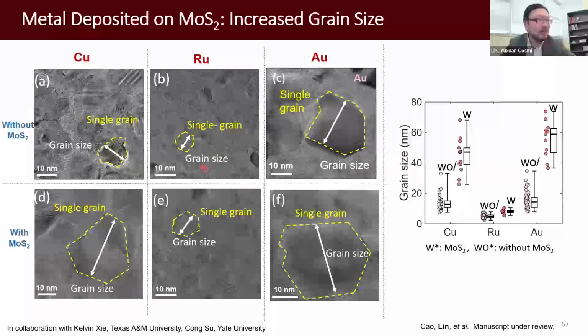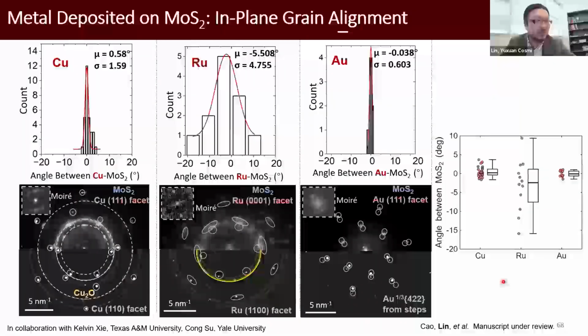Without MoS2, we see smaller grain size. With MoS2 underneath, we see increased grain size. Here are the statistics. So for each metal, we see a significant increase of the grain size. That's encouraging. We also use the diffraction or FFT to figure out the alignment between different metal grains, and we categorize on different images to get the statistics.